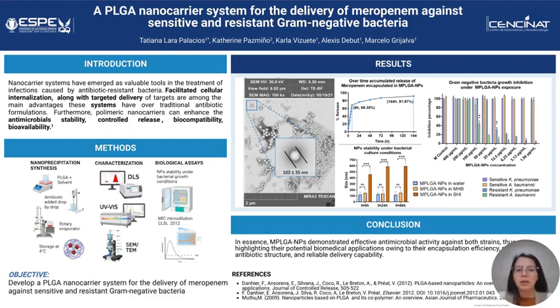The resulting nanoparticles were characterized for size and morphology by dynamic light scattering and scanning electron microscopy. The drug encapsulation efficiency and release kinetics were analyzed by UV spectroscopy, and subsequently we tested the nanoparticles' stability under bacterial growth conditions with culture media and temperature. We assessed the nanoparticles' functionality for meropenem delivery in Klebsiella pneumoniae and Acinetobacter baumannii meropenem-resistant and sensitive clinical strains with the minimal inhibitory concentration microdilution method.